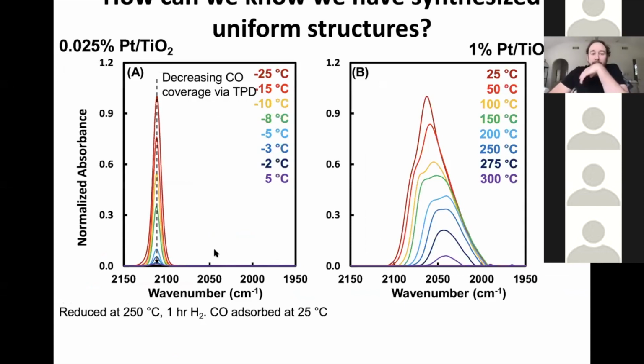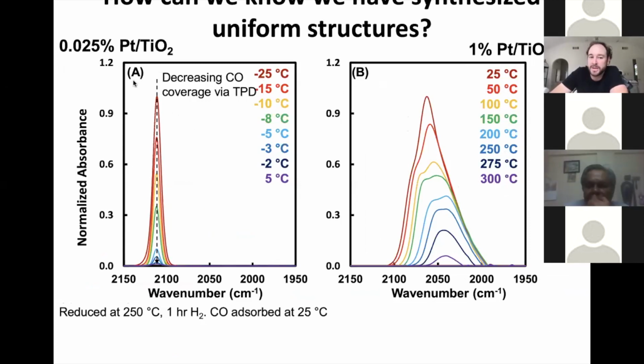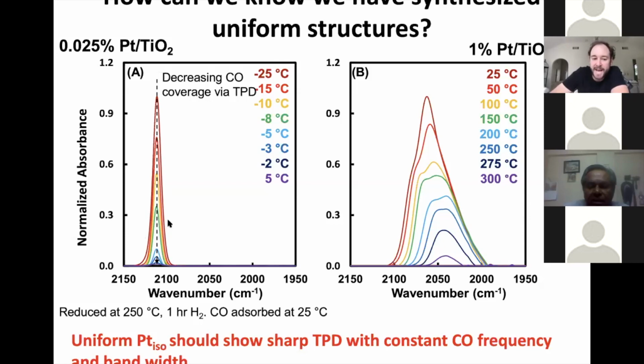So, the next way that you can assess uniformity is you can do a TPD. You can see CO TPD from the sample that had lots of clusters here, shows band positions varying as a function of coverage, and you can see desorption over a really wide temperature window. When CO desorbs from what we think is our sample that has only isolated platinum species in uniform positions, you see the band drop straight down. So no change in the full width half max, no change in the band position. This tells you that the dipoles of the COs are not interacting, and so these are spatially distinct from each other. So this is the second thing you should convince yourself of before you go and try to make a structural assignment, that you actually have uniform species.